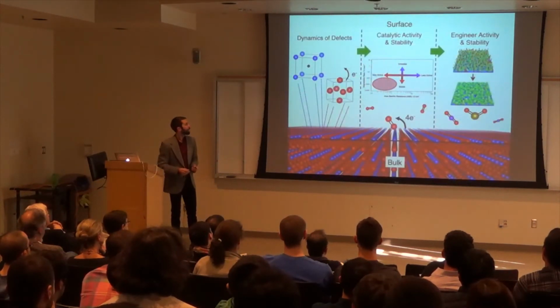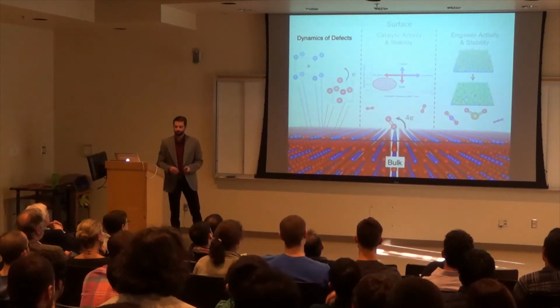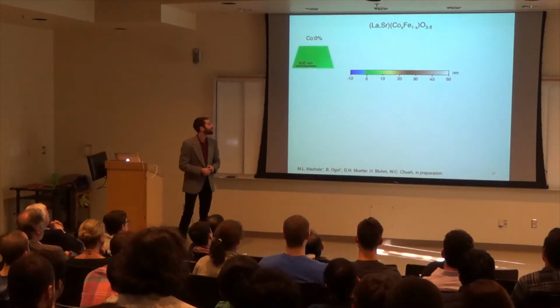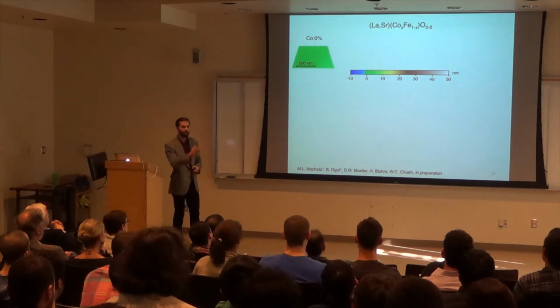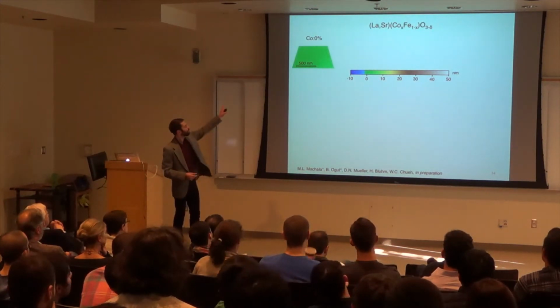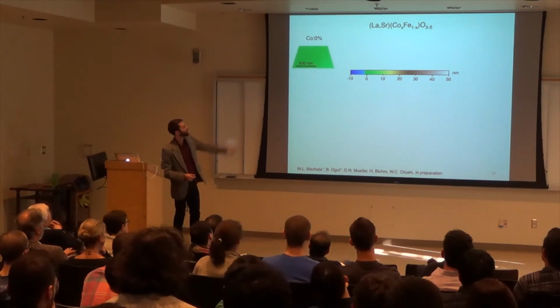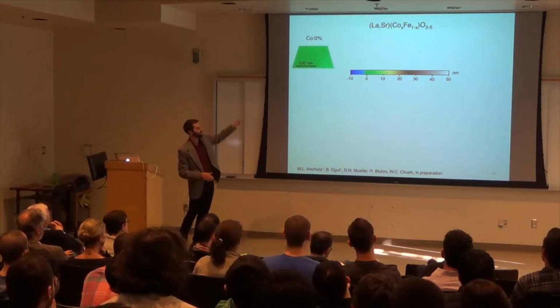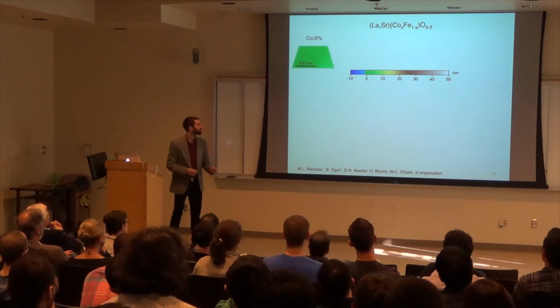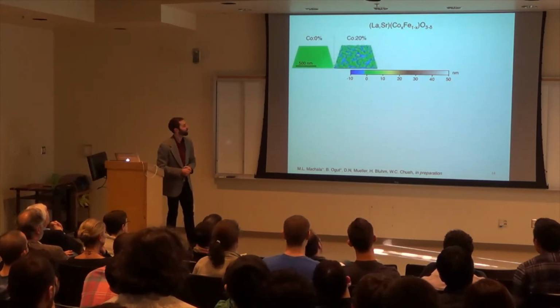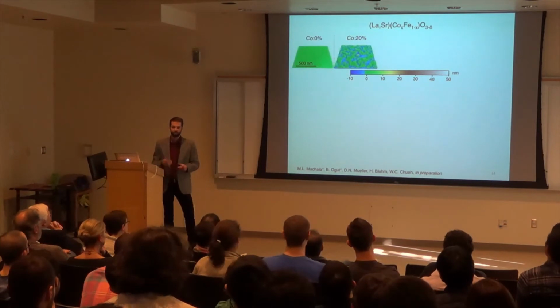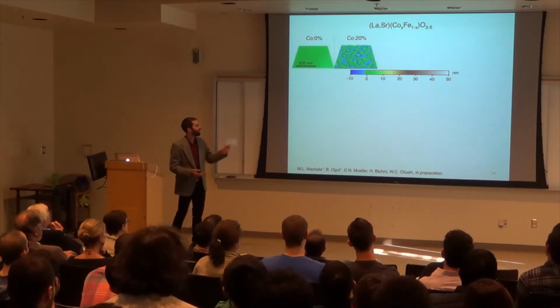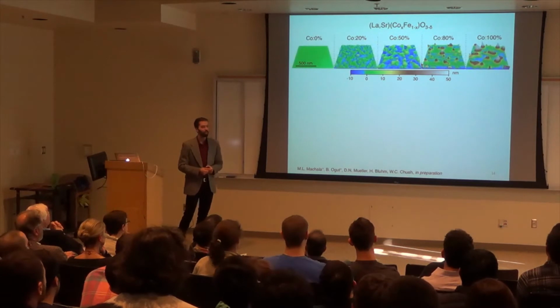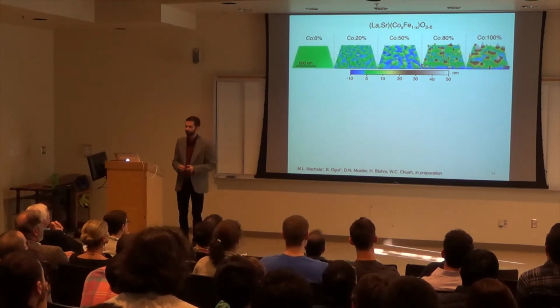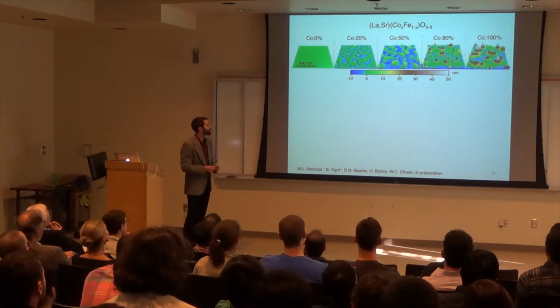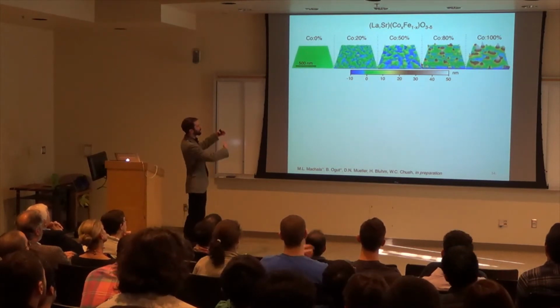So first up, I'm going to focus on the bulk of the material. I've already mentioned to you this lanthanum cobalt iron series where we add cobalt into the material system. Shown here with just 100% iron on the B side, the surface looks relatively flat. This is an AFM micrograph. If you start to add cobalt, you see the surface begins to roughen, showing that there's something going on as you add cobalt. And the trend continues when you go into 100% cobalt, where you get these large islands and large bumps forming.